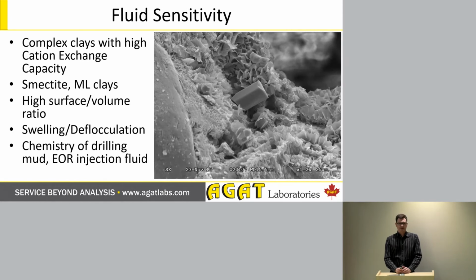What we have in these sands is a lot of very complex clays with high cation exchange capacity, in particular smectite and mixed layer clays. In the image to the right here, we see a well zoomed-in scanning electron microscope image of a pore system within this rock. What we have is a very prominent zeolite crystal that has mineralized in the middle there, but it's sitting on a bed of petal-like corrensite, which is a mixed layer clay. And so we have a very high surface to volume ratio of these clays, and this gives us a situation that's ripe for the problem of swelling clay.